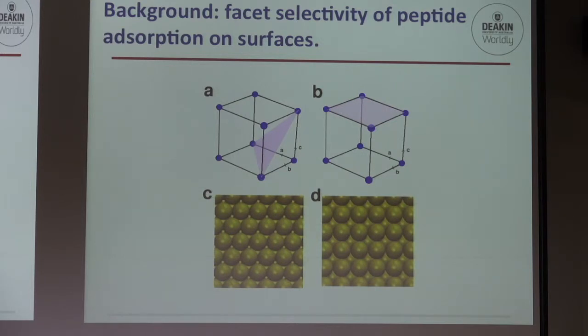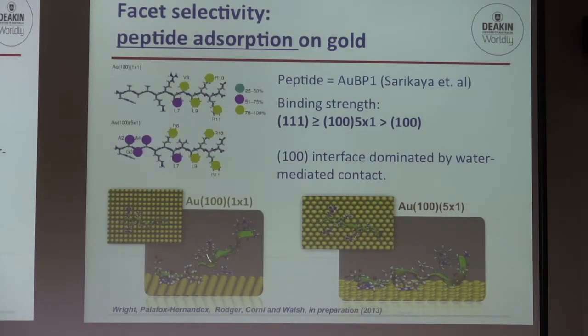So you don't even have to change the chemical composition. You can make a change as subtle as this and see remarkable differences. So this is some work that we're just about getting wrapped up, where we're able to calculate the binding strength of these peptides onto different facets of the gold surface, and what we see is a distinct difference in the binding energy, and we're also able to relate that back to the structures. So you can see here some of the structures on the surface where things don't bind so well is because half the molecule is just sort of waving off and not very engaged with the surface. Whereas in the other cases, it sticks on a lot more evenly and readily. So it's being able to identify those parts of the molecule that stick well onto various facets that can enable us to design new sequences.